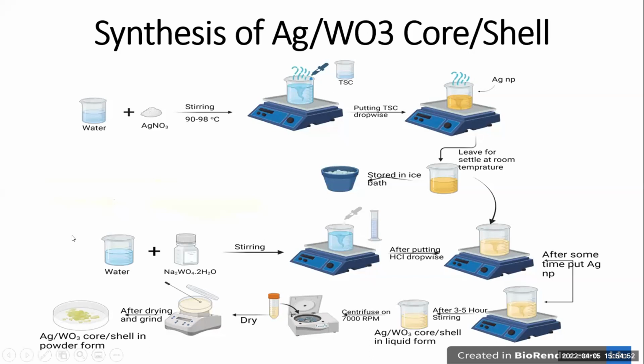After Ag nanoparticle synthesis, we start WO3 synthesis. Same, we took distilled water in a beaker and we put sodium tungstate dihydrate and stirred for some time, and after some time we put hydrochloric acid dropwise, 1 drop per second. After some time we found a light yellow color of WO3 nanoparticles, and when we found the light yellow color, we put the Ag nanoparticles in the solution. After 3 to 5 hours of stirring we found the Ag-WO3 core-shell in liquid form. After centrifuging at 7000 rpm to wash and dry, we found, after drying and grinding, the Ag-WO3 core-shell in powder form.